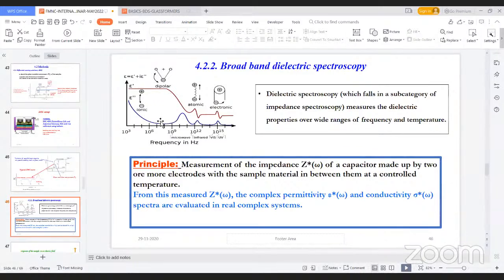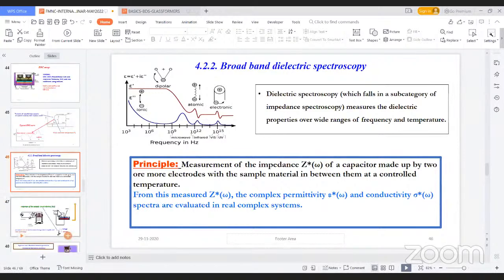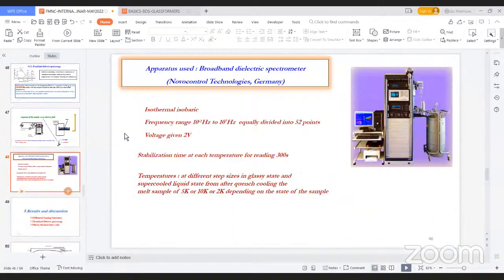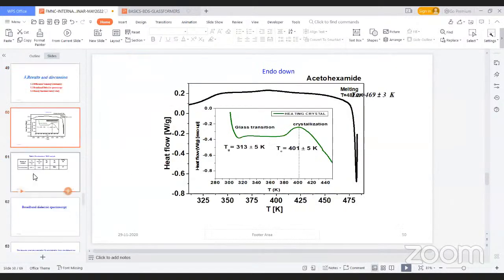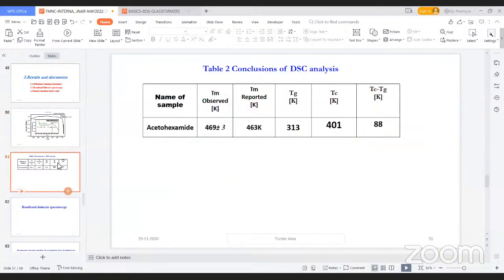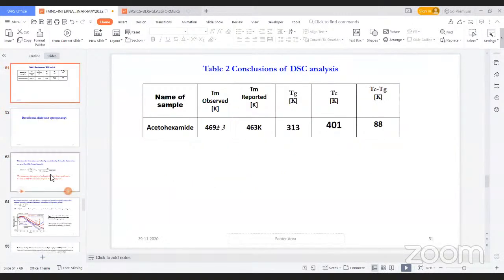So if I have data for different temperatures, we'll get a BDS spectrum, that is broadband dielectric spectrum. These curves at the different temperatures will give you some parameters which are crucial to estimate the stability of the amorphous phase. The apparatus used is shown in this figure. This is the DSC curve of the acetohexamide. The glass transition temperature is shown in this table.